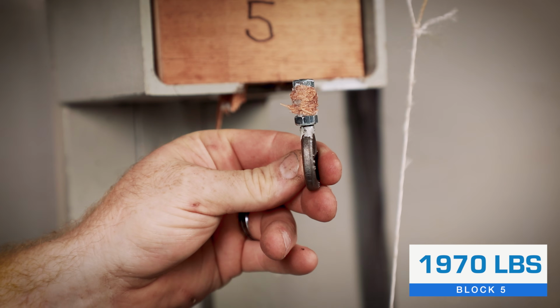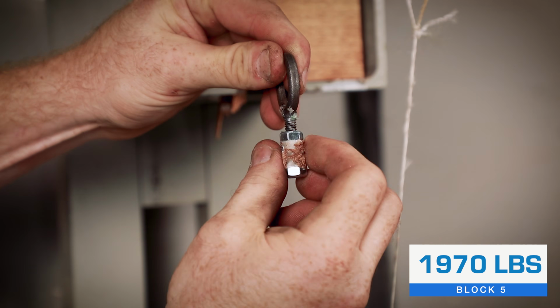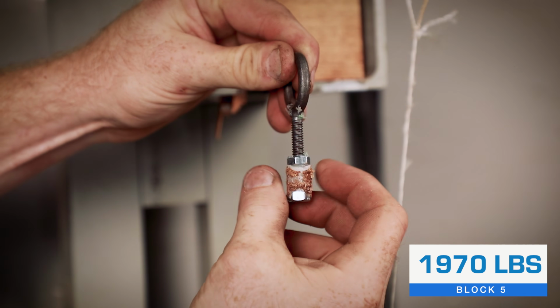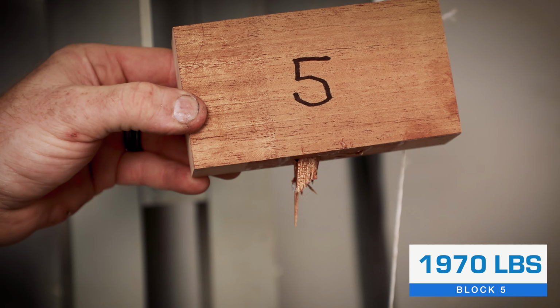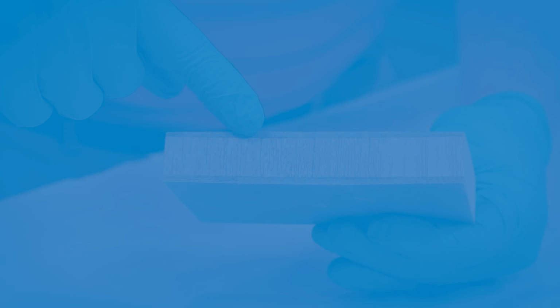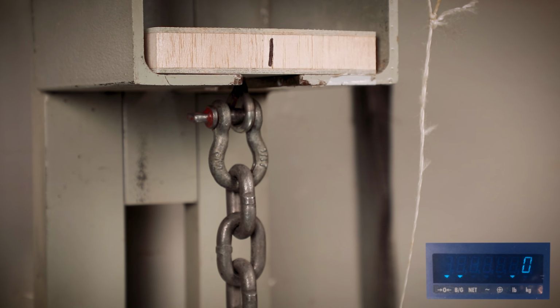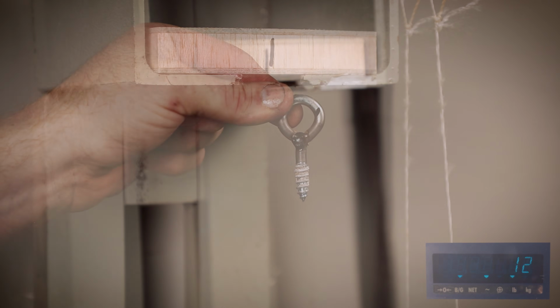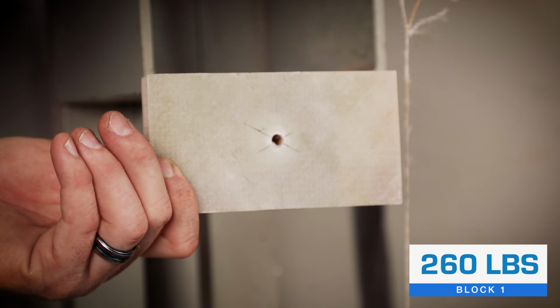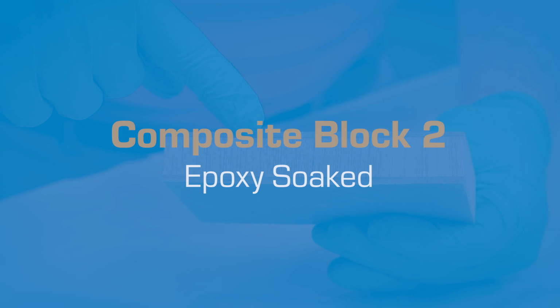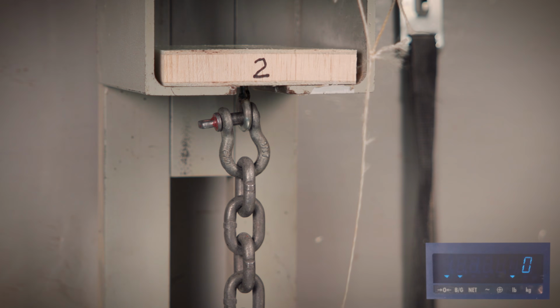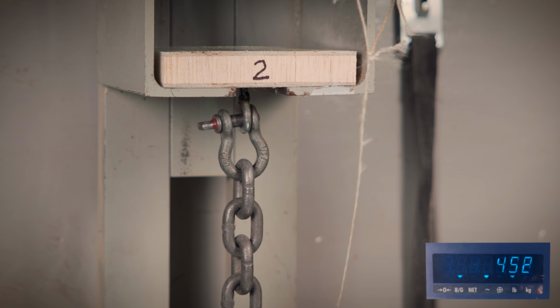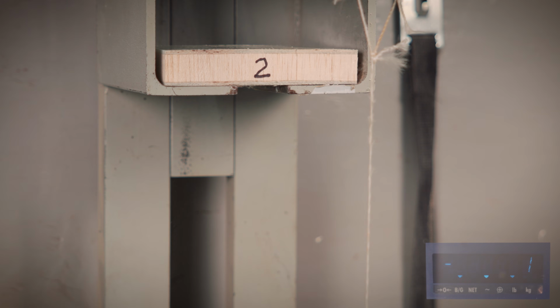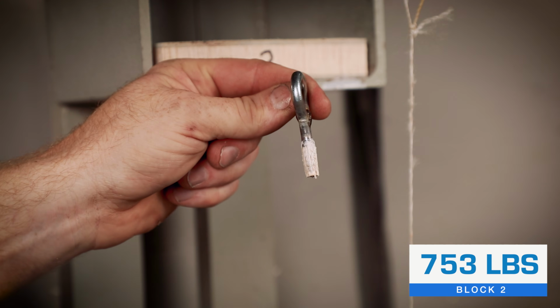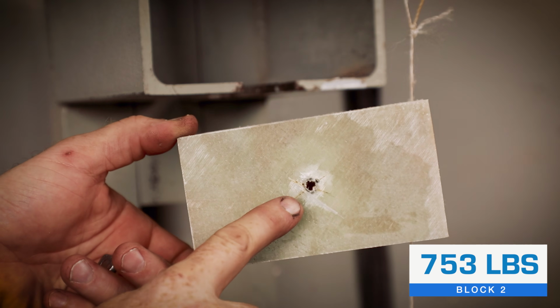For block number 5, the fastener pulled out of the block with a large amount of wood failure and the nuts can be removed from the fastener. For composite panel number 1, the fastener easily pulled out of the panel with minimal wood failure. For composite panel number 2, the fastener pulled out of the panel with balsa remaining on the fastener with minimal damage to the fiberglass laminate.